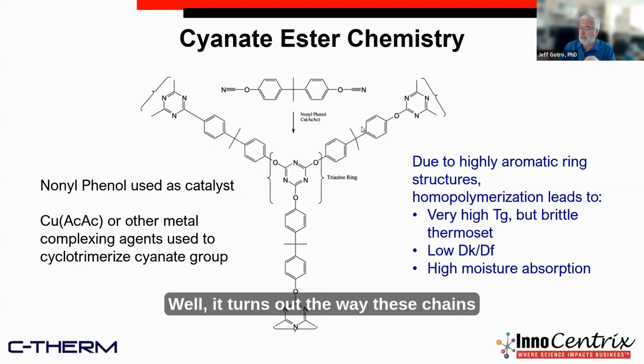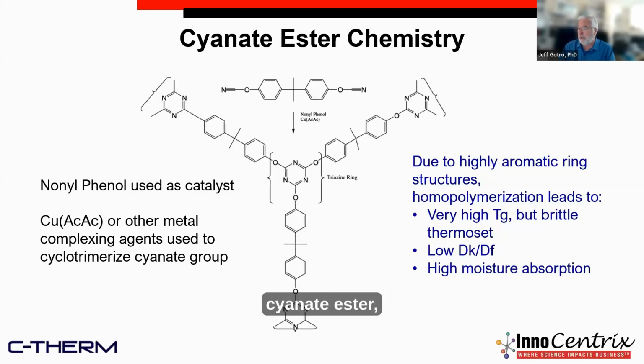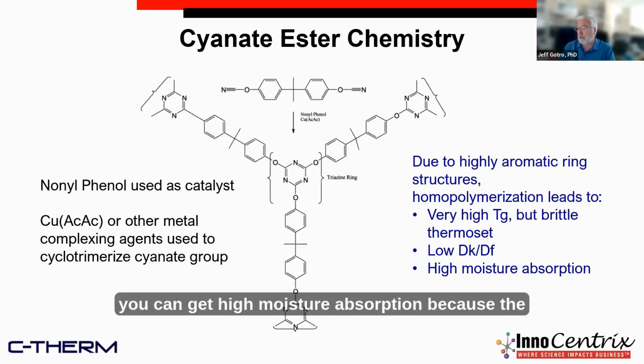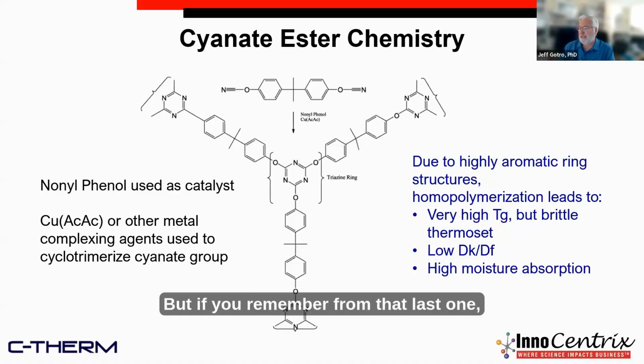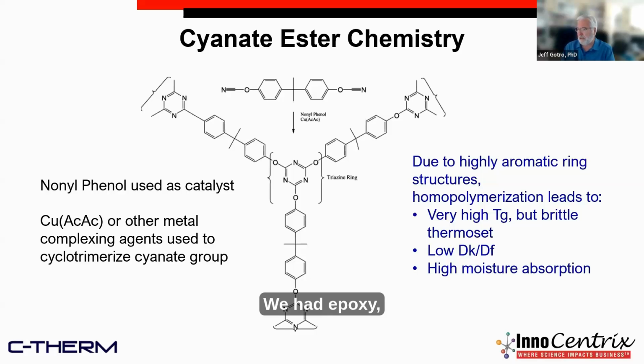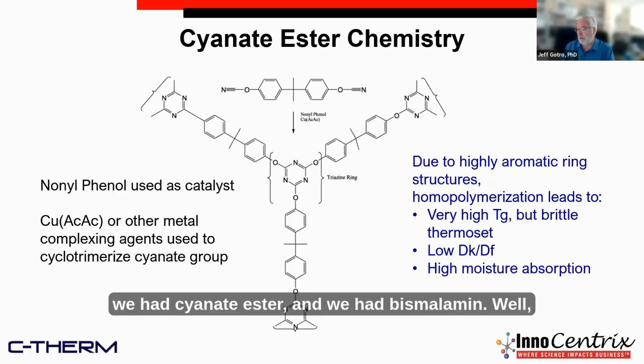Well, it turns out the way these chains sort of polymerize and pack, there's space in between the chains. So if you just use straight cyanate ester, you can get high moisture absorption because the water kind of wiggles in between the chains. But if you remember from that last one, the last slide, we talked about the BT system. We had epoxy, we had cyanate ester, and we had bismaleimide.